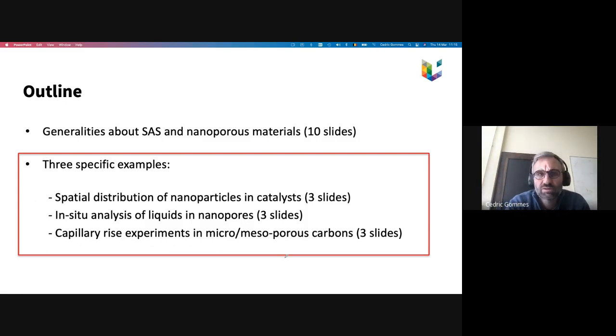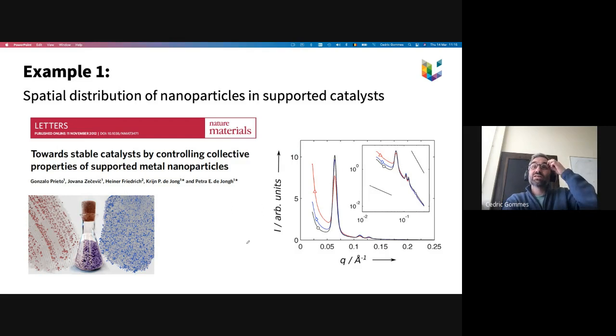So the first example I talk about is the case of spatial distribution of nanoparticles in supported catalysts. This is some work that I did a few years ago with colleagues from Utrecht. They were preparing a supported catalyst. You see these images here; those are from electron tomography reconstructions, so 3D TEM reconstructions. This was a mesoporous silica, you see pores here. The scale is about 10 nanometers. Depending on how they prepare the catalyst, they managed to have a homogeneous distribution of these copper nanoparticles inside the pores, homogeneous or more heterogeneous.